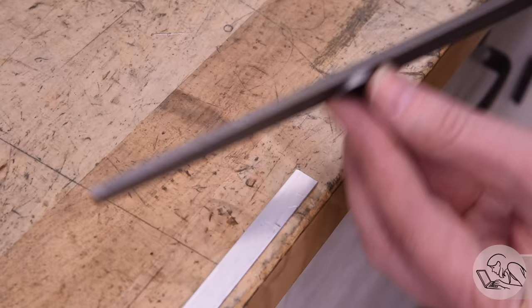Here's a small punching tool that I heat treated recently, and I'm going to show you this because it's got all the colors on it. At the far right end, we've got the lightest yellow color. That's going to be the hardest. Then it transitions into the yellows and browns, getting a little softer, softer, and then it goes into the purples and the blues, softer still, and then left of the blue there, softer still, but not fully annealed yet.